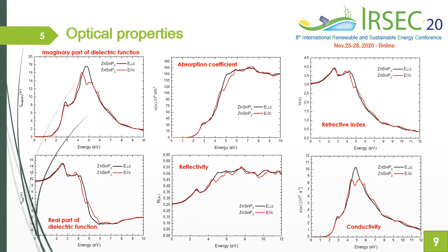The optical properties are considered an important source of information concerning the electronic band structure. They are usually deduced from the dielectric function. Here we show the various optical parameters in these figures, such as the two parts of the dielectric function, the reflectivity, the refractive index, the optical conductivity, and the absorption coefficient within mBJ under ordinary and extraordinary polarization.